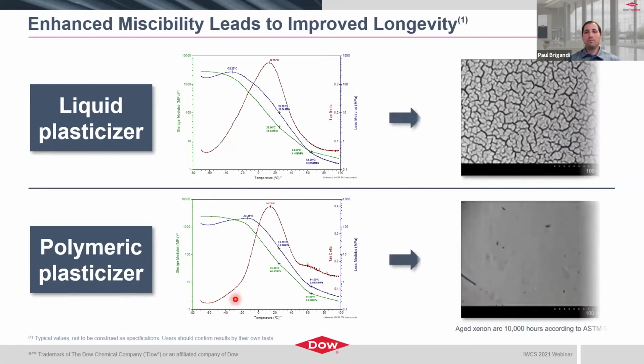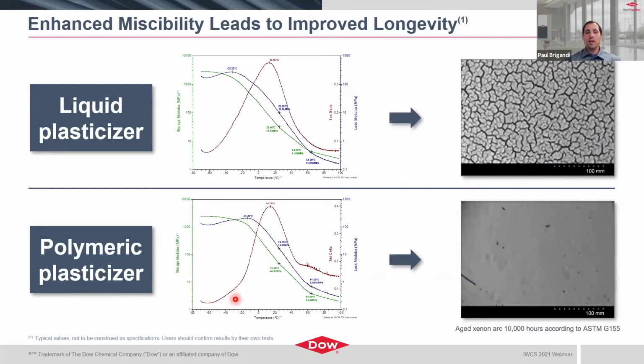And what does this mean over time? If we look at some aged samples, these are aged under xenon arc for 10,000 hours, just representative of UV aging. When you look at the case of the plasticizer that is based on liquid, over time you tend to get the migration out because of its low molecular weight, and you start to see cracking within the material. This is just a representative sample that shows the cracking after aging under UV conditions. Conversely, when we look at the polymeric plasticizer, we see a nice homogeneous and uniform piece of material still left behind. The polymeric plasticizer is going to remain in the material, and that material is going to stay flexible and more resistant to cracking over time.